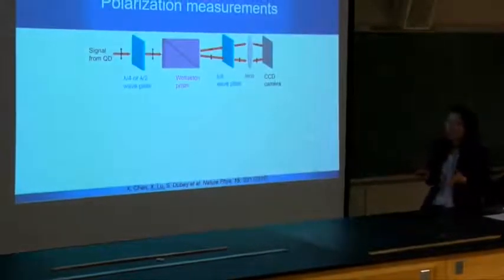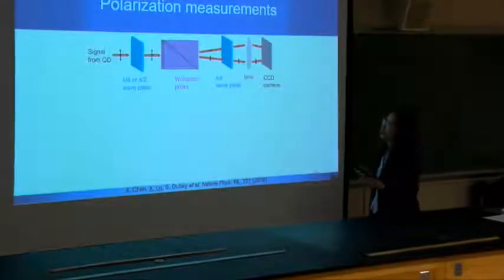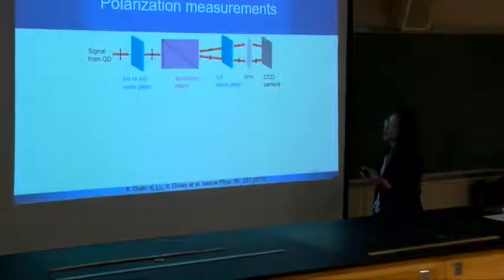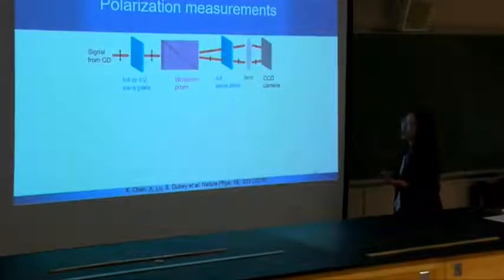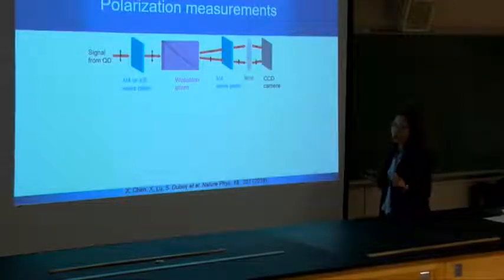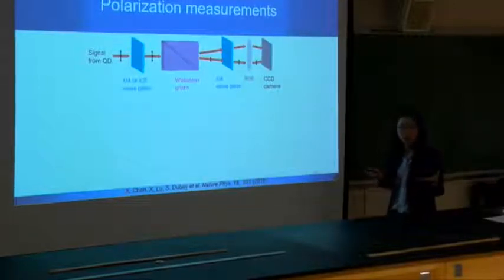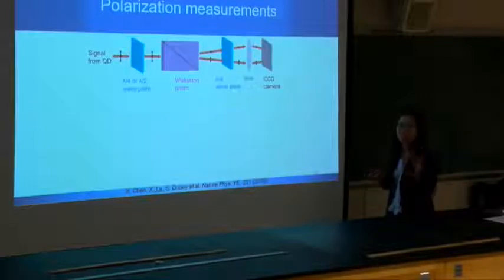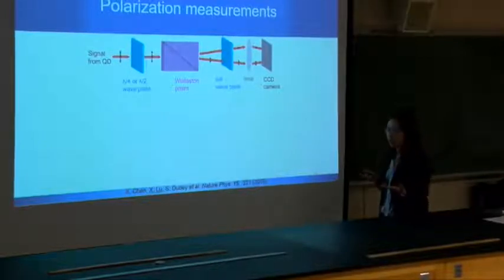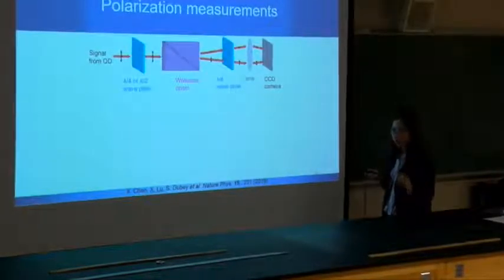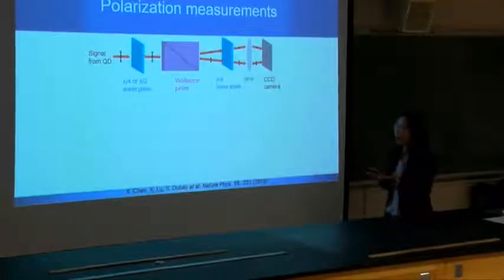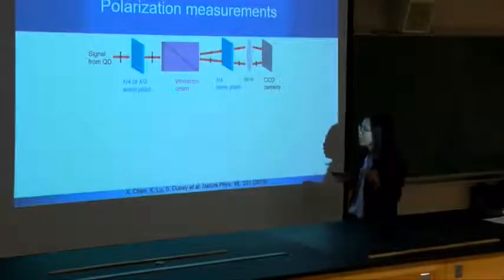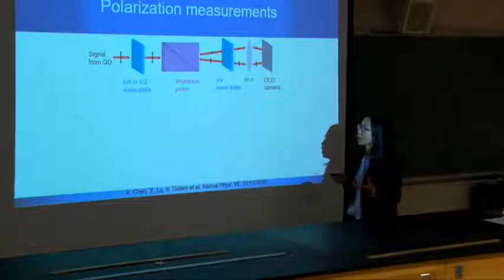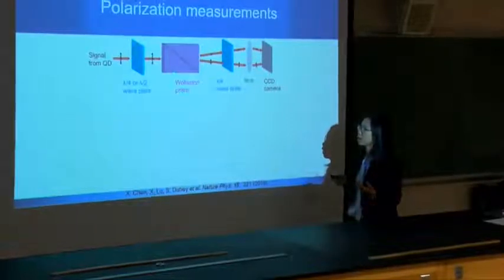The interesting part, or the puzzling part, is from the polarization. So this is the simple schematic we use to measure the polarization. One of the important characteristics of a quantum dot, a quantum emitter, is that it blinks, just like a star. Sometimes it's very dark, sometimes it's very bright. So to eliminate that fluctuation in the measurement, we use a Wollaston prism.